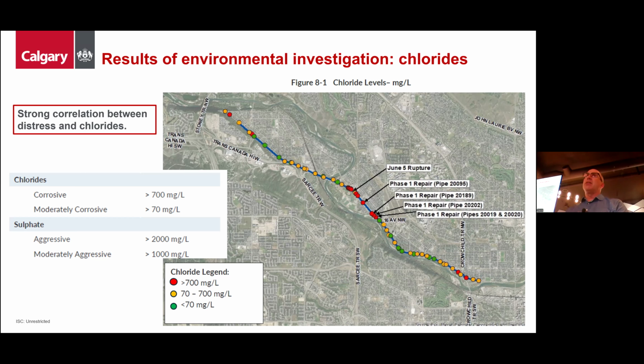So what we had in about 2004, 2008 was a feeder main break up at McKnight. And McKnight, the pipe, again, PCCP, was subject to a sulfate attack. So the pipe actually, the mortar had become talcum. So it was falling apart. It had caused attack on the pre-stressed wires, and then the pipe broke in that form. This was not the case with this, where we're not seeing any sulfate attack. It was actually predominantly chloride attack. So that did take us by surprise.